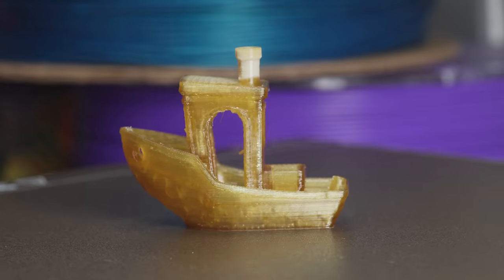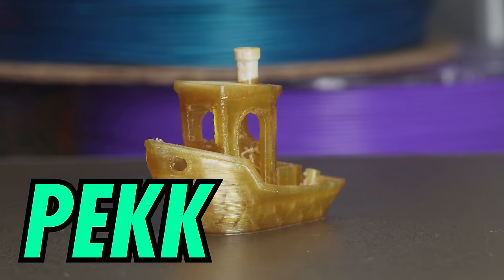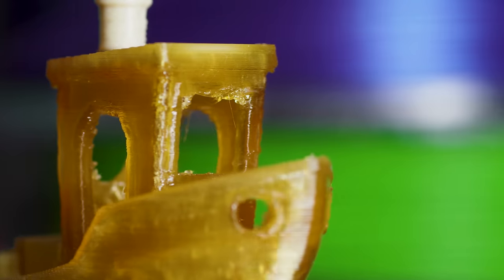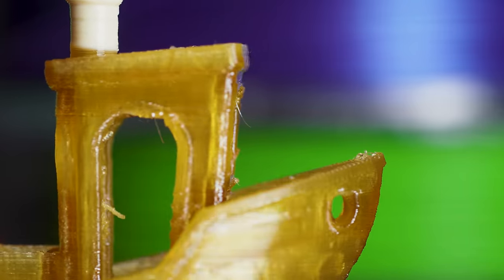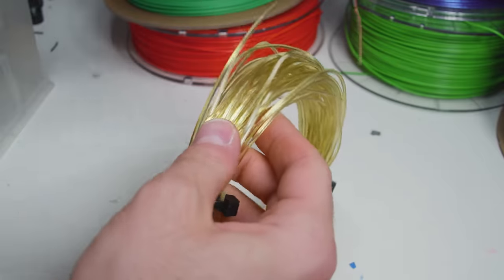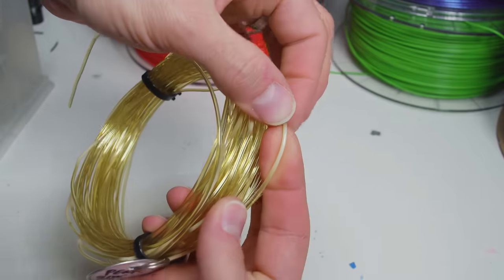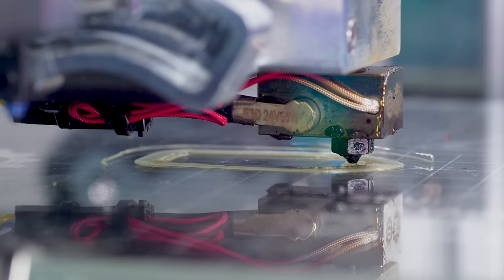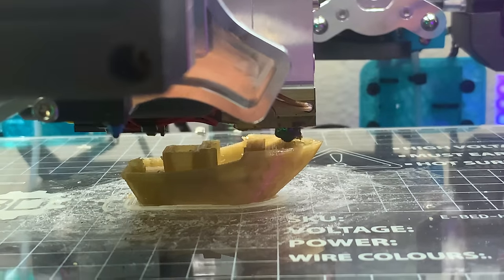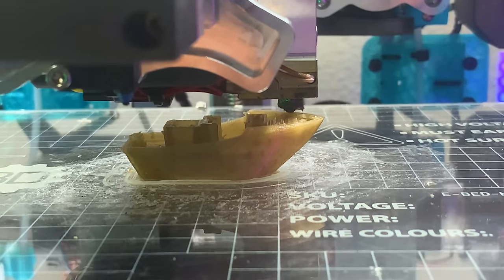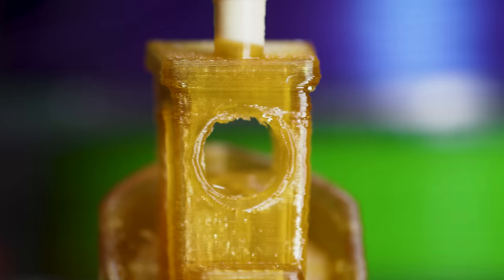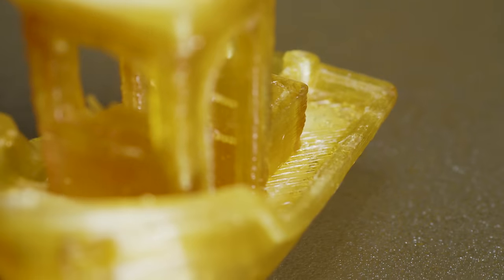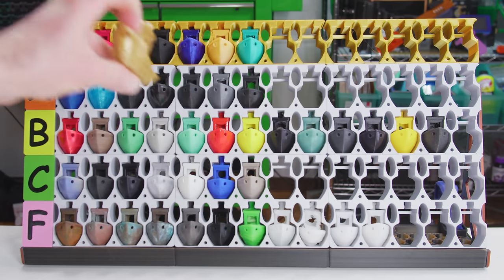If you can concede on one or more of those stats, another superpolymer will give you a much bigger bang for your buck. PEEK, for example, PEEK's little sister, PEKK. Polyether ketone ketone is the same chemical building blocks as PEEK, just in different proportions. Its mechanical properties are all worse, but compared to regular filaments, still off the charts. PEKK, like PEEK, demands a lot of your printer, but once you pass the gear check, this is one of the easiest polymers to print full stop. My tool changer doesn't have a heated chamber, but I still managed to nail this beautiful benchy on the first try. I think PEKK deserves the A-tier. Even though PEEK beats it on paper, a PEKK print is almost as strong, and it's far more likely to succeed.